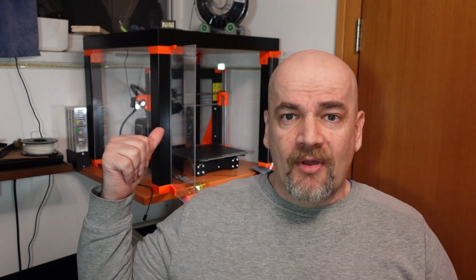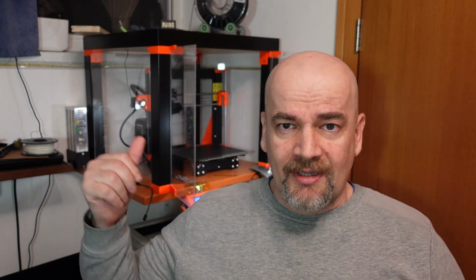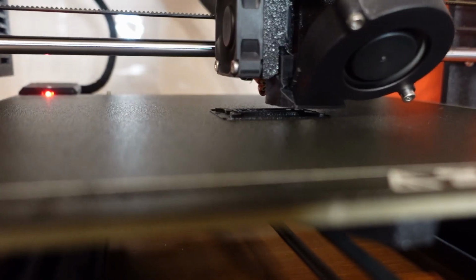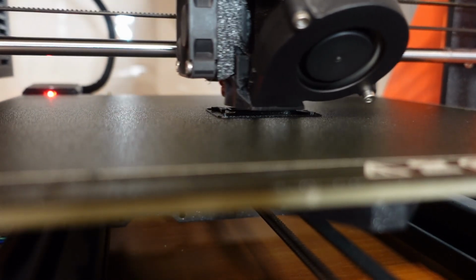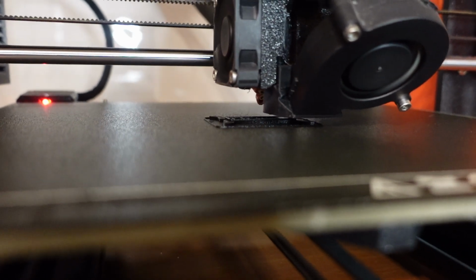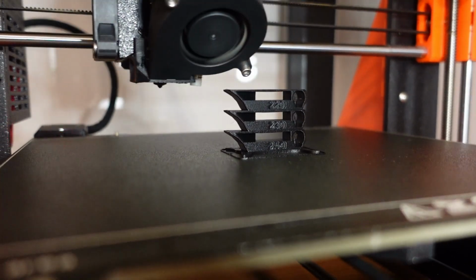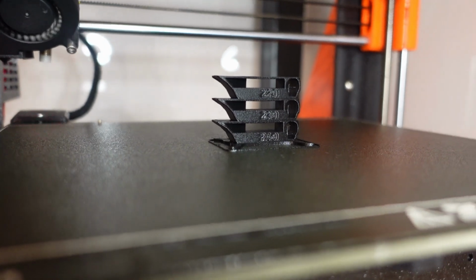Anyway, I will try with 0.4, but I will be here continuously to follow the printing, because if I hear that the extruder is skipping, maybe I have a clog and I have to stop the printing. I want to use a 0.4 mm nozzle because I want these test objects to be more comparable with each other. This is the start of the temperature tower without any problems, it sticks well. And look at this perfect printing, absolutely no problems on any elements.